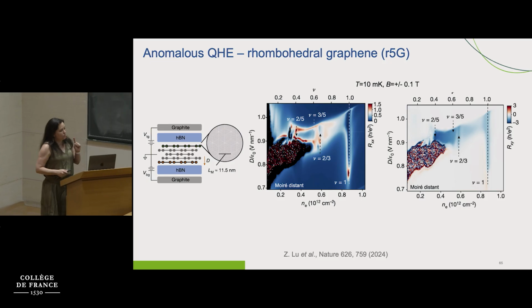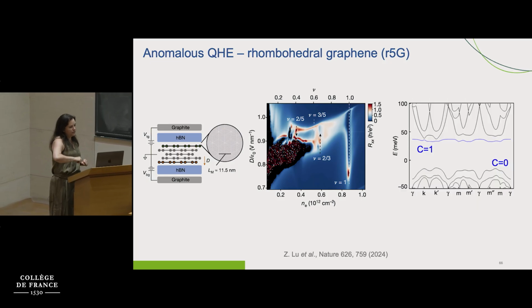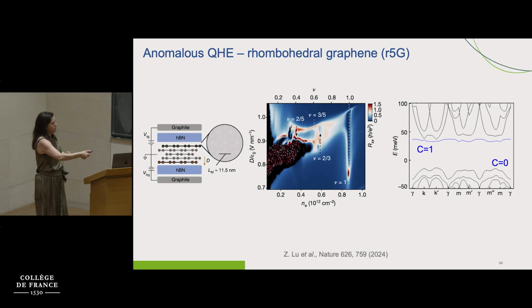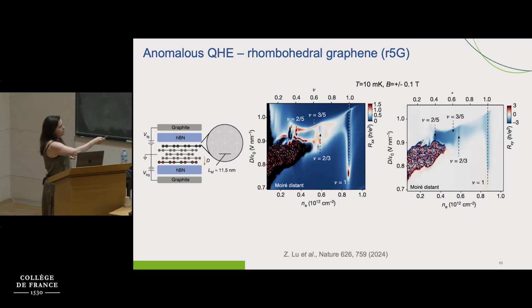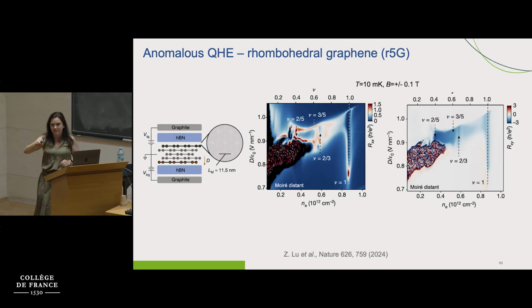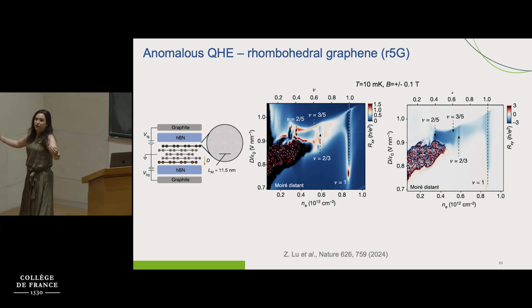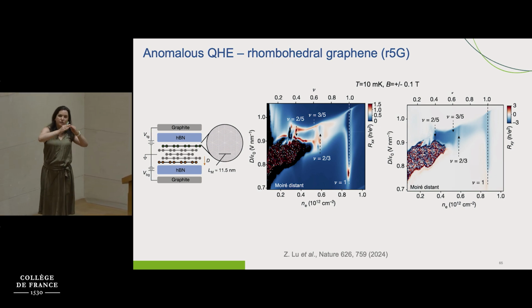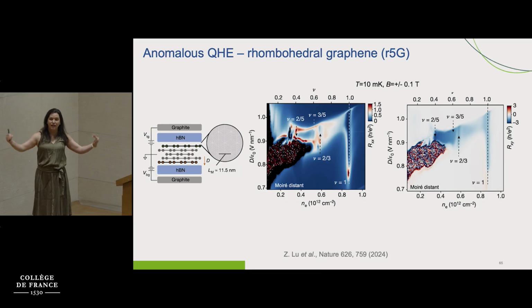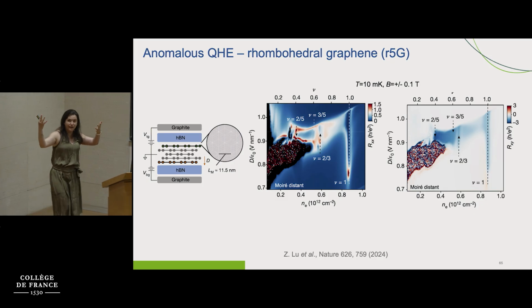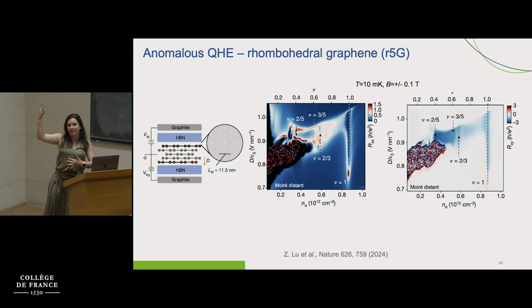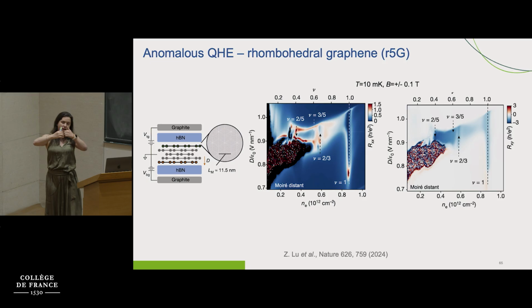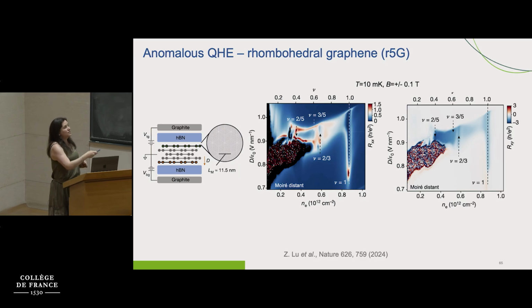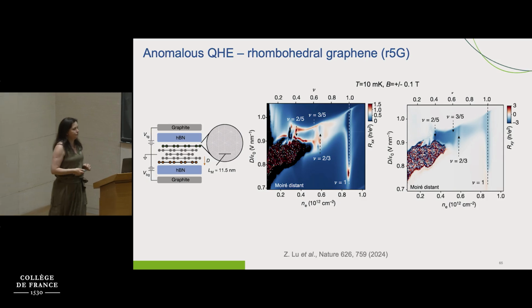But okay, what is also very interesting, the other thing that is important to keep in mind, is that this is Moiré-distant, but it's not pushing the wave function to a place where there is no Moiré, because remember this commensurate state I told you before will propagate to a certain number of layers. We don't know how far it's going to propagate, but we know that at least to 10 layers, we can still see the Moiré, the commensurate state. So it's just Moiré-distant, but not a Moiré-less part of the diagram.